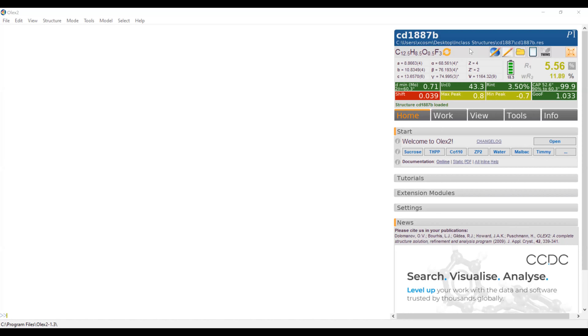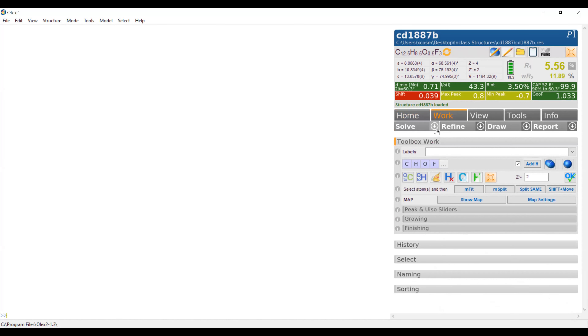I've already gone ahead and opened up the .res file here. It just contained information like the unit cell, chemical formula, errors in the unit cell, the symmetry operators, the Z value, and things like that. There's no atomic positions or anything of that nature. The I over sigma is pretty good — this is very good data at 43. Ten or better is what we're looking for. Rint is pretty good at 3.5%. You see the majority of these are green, so let's solve it.